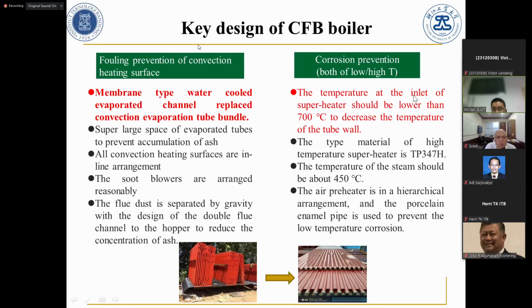About the corrosion, the temperature at the inlet of the superheater should be lower than 700 to decrease the temperature of the tube wall. Of course, if it is lower than 700, your steam temperature, the superheated temperature, cannot be higher. So 450 centigrade usually. The material of the high temperature superheater is TP347H, and the steam temperature should be about or less than 450 centigrade. And the air preheater is in hierarchical arrangement, with porcelain. This is the material, right? Just like crystal or glass type, used to prevent low temperature corrosion.